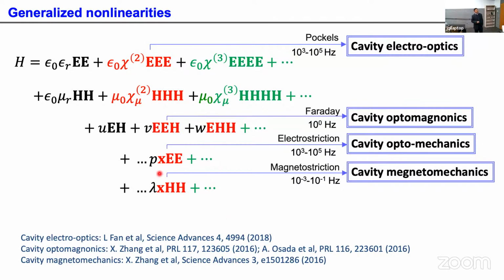Of course, you have even other orders of terms. There's magnetostriction that also can give you frequency mixing, but those are much weaker effects. So in most of the systems that we utilize for microwave to optical conversion, even optical to optical conversion, we normally use the electro-optical Pockels effect or Chi2 effect or cavity optomechanics, because the single photon coupling rate is always bigger.